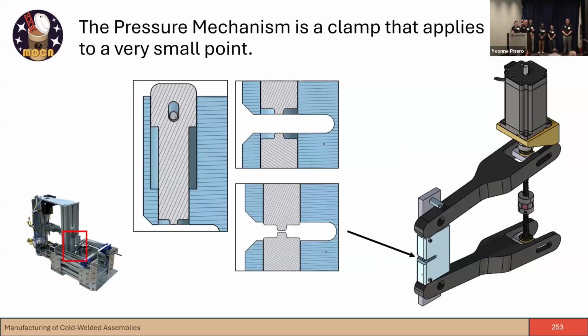And here, to make it a little bit clearer what's going on, is a cross-sectional view of the crimp head. There's a pin that transfers the force from the NEMA 23 motor and through a forward threaded and a reverse threaded 3/8 lead screw. That forces those two levers apart and then concentrates that force on the ends of the two pins. You can see in that bottom right cutout the closed position of those pins and the smaller protrusions there. That's what actually causes the plastic deformation in each of the welded samples to promote that atomic diffusion and get a good atomic bond between the metal atoms.